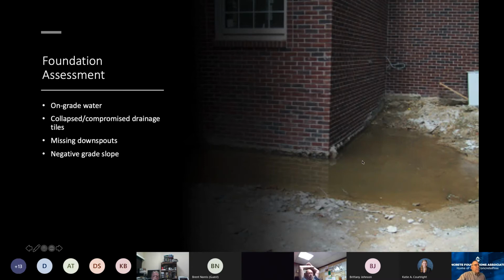Here's an example, though, of assessing the foundation wall cracking. If I see leaking going on the inside, if I start to see cracks that open up where they weren't before, and I come around the outside and I see something like this, obviously I don't have positive grade away from the foundation, and I've got water that is congregating and accentuating the soil pressure. And I might go from a design of 45 pounds per square foot soil load up to 60 or 70 or maybe even 75 pounds per square foot, and that wall wasn't designed for it. I get a moat that begins to build up around.